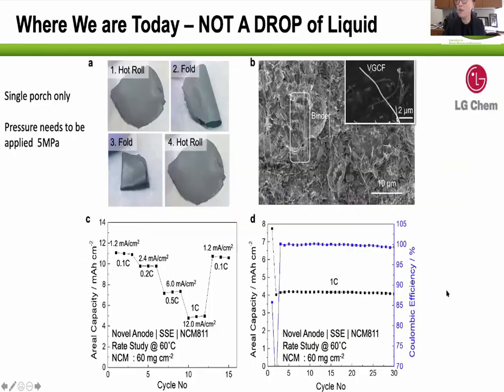Okay, so what we have done today at UCSD is that we can at least make solid state batteries without a drop of liquid, no liquid at all. And the applied pressure is 5 megapascal. We can actually cycle pretty well at 60 degrees Celsius. I'll tell you, we're nowhere near room temperature cycling with lithium metal. Hopefully, we will report very soon. With a different anode strategy, it might be possible, but this is still only a small lab scale test.